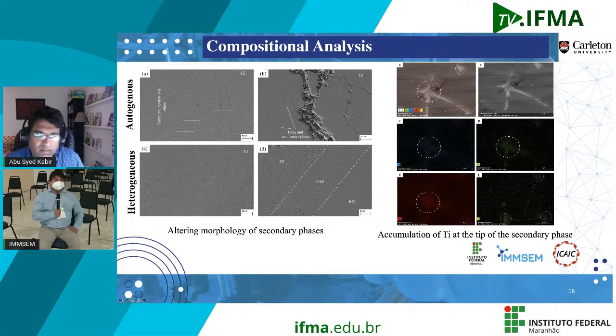And if we actually take one of the heterogeneous precipitates here in the area scanning and EDS mapping, we see that this is one of those precipitates on the heterogeneous joint, and we see that the precipitates are mainly zinc, copper, and magnesium. We do have all those elements in the structure, but we see some traces of titanium all at the corners of the precipitate, at these different regions.